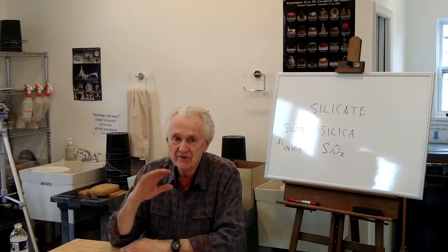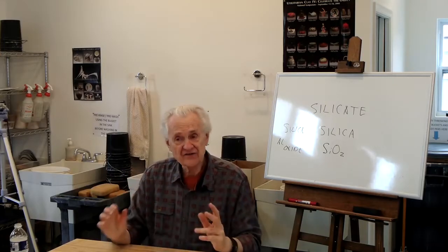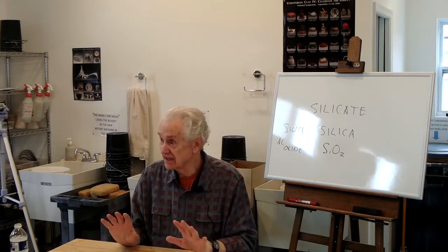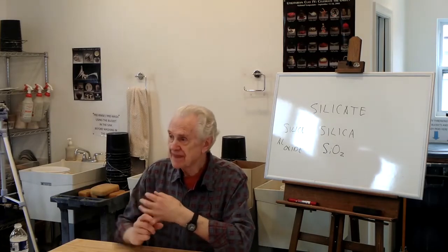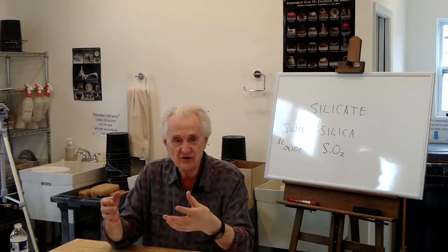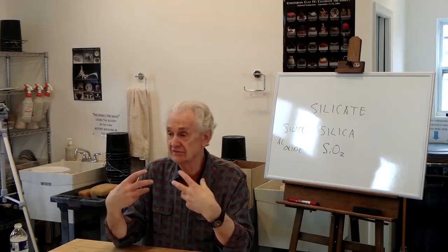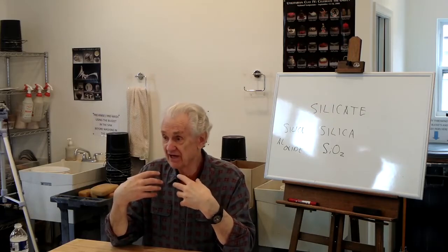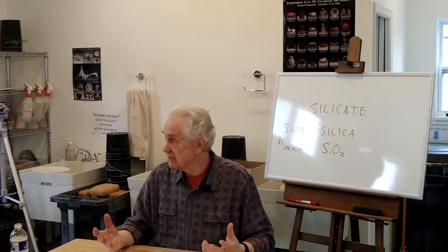And he started thinking that when he looked at glazes, we can group the oxides in a glaze into 3 categories. And we need those 3 categories in a glaze. The first is what he called the glass former, that is, the ingredients that actually make the bulk of the glass. He called them the glass former elements, and we'll talk more about those. In our case, it's silica. Our glazes are mostly made out of the compound silica. So that's the glass former for most of our glazes.